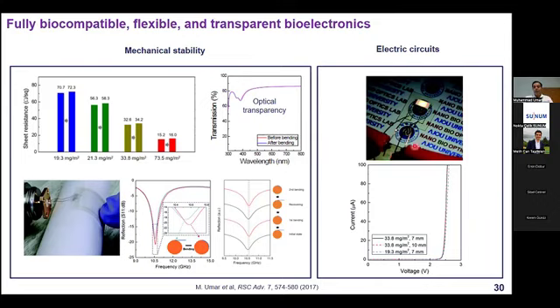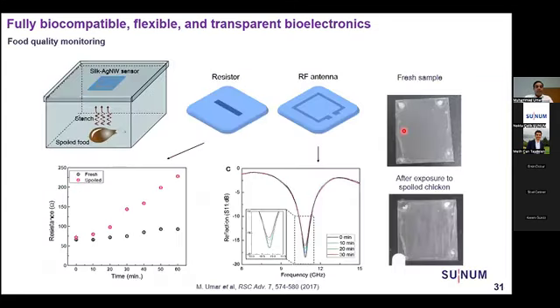On the other side, we show that the silver and silk electrode could be utilized in electronics. We just turn on an LED by connecting a silver nanowire network in the silk, by applying a voltage of just 2.3 volts, because of the high conductivity of this electrode. So this means this electrode could be utilized in electronic applications.